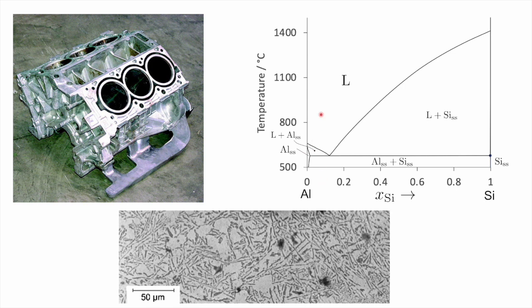And when the material is cooled, the first phase to form will be a pro-eutectic aluminium-rich phase, followed by this eutectic mixture of silicon and aluminium. Now, the silicon has almost zero solubility for aluminium, whereas aluminium can dissolve a certain amount of silicon. In fact, the alloy is not just a mixture of aluminium and silicon. There are other elements included. I won't go into them.